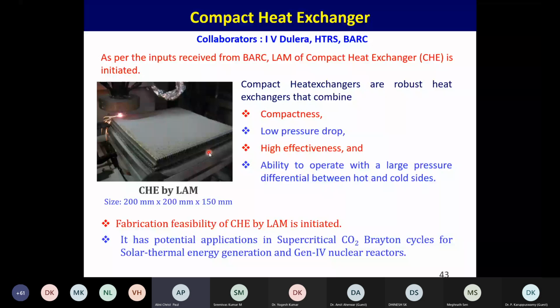They do diffusion bonding. What they do is acid etching to make the channels, and after that they stack all the plates and take them for diffusion bonding in the furnace. So that is the way it's done. And the cost of these heat exchangers by the conventional process is in the range of 70 to 80 lakh rupees.